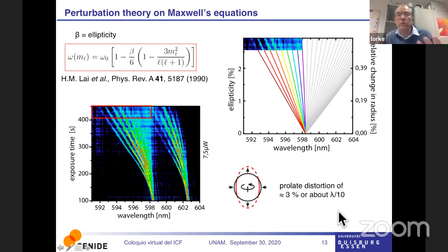And this again shows you how sensitive these whispering gallery modes are to very, very small perturbations. And people use this. They can, for example, have a sphere and have molecules attached to the surface. And that, of course, changes the dielectric environment of these whispering gallery modes. And therefore, they will change their frequency. And therefore, you can use this, for example, for chemical detection purposes.